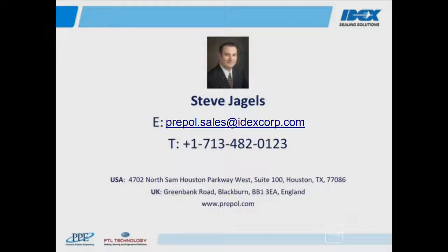Okay. What are the typical compression set values? Yeah, these days with the modern perfluoroelastomers, those that have been on the market, say in the last 10 years or so, most of them have reasonably good compression set values. So let's just say on an O-ring test, 70 hours, 200 degrees C, I would expect to see a compression set around 25%. And that would be in hot air.